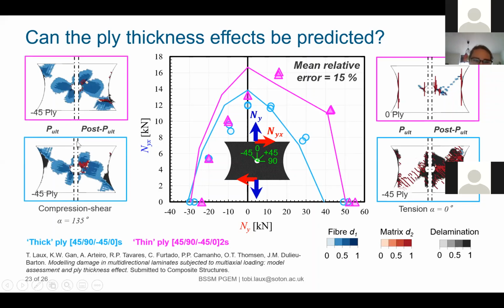Whereas in the compression side, if you look at these patterns for the thick and thin ply laminate, they look pretty much the same. So you have some fiber kinking failure. It's compressive here at the hole, at the dark blue. So you can see this in both specimens in the same ply. And you have some delamination going on at the edges. So that explains a bit why the strengths are similar here.